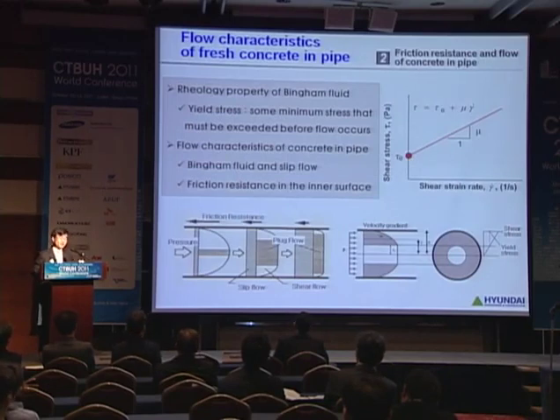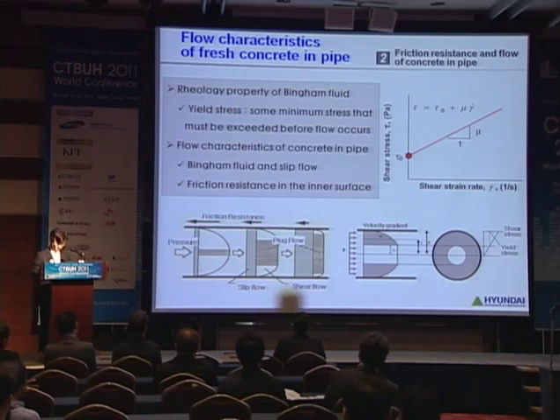Well, what are the characteristics of fresh concrete flow in pipe? Concrete is liquefied solid with yield stress and plastic viscosity. Unlike ordinary sticky liquid, the concrete flow in pipe is very complicated. Because of its characteristics, the loss of inner pressure with the distance from pump is caused by the plastic viscosity of the concrete and the inner surface friction of pipe. Especially, the inner friction resistance inside pipe is the most significant element for evaluating the pumpability of concrete.